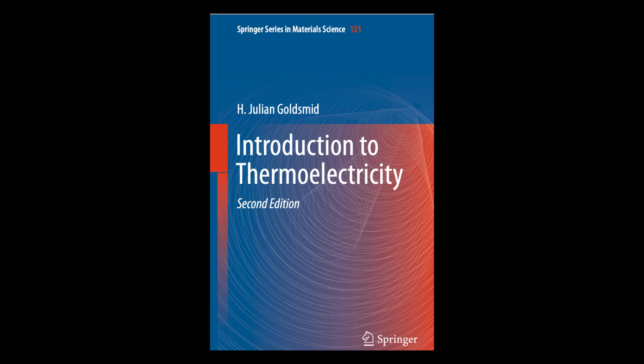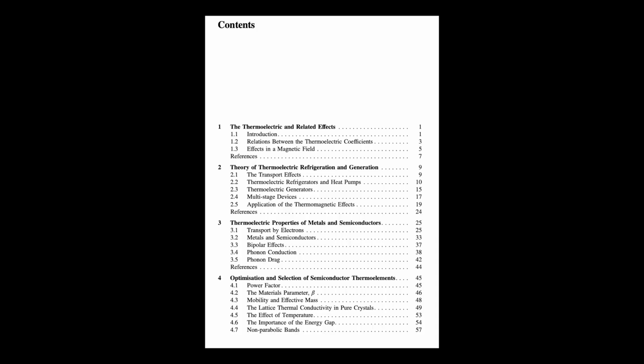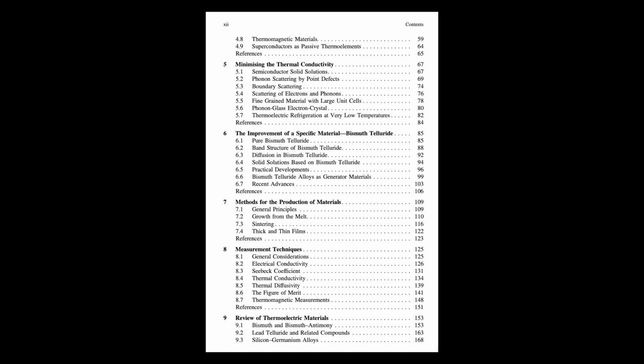Big issue at high temps is heat loss via radiation. Throws off the measurement, so transient methods are popular. The 3-omega technique is great for thin films or poor conductors. You use a heater strip on the sample, drive it with AC current at frequency omega. This creates temperature oscillations at 2 omega. You measure a tiny voltage oscillation at 3 omega, which relates to the thermal conductivity. There are also radial flow methods. But yeah, always need careful corrections for heat losses.